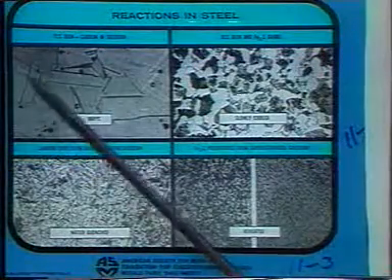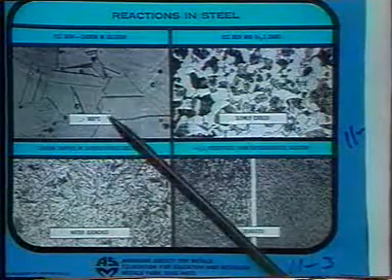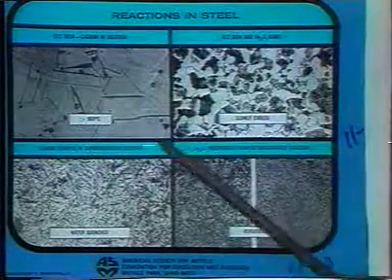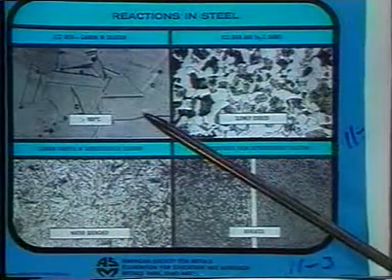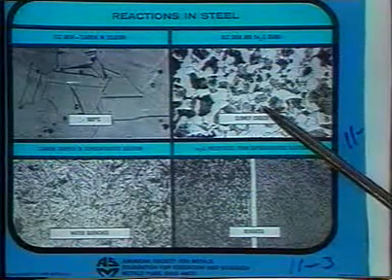Actually, these perfectly straight lines are also crystal boundaries, but they are special crystal boundaries called twins. But all of these things are crystal boundaries, and it's no identifiably different material. The little pockmarks you see in this particular case happen to be holes in the material, but it's not a solid state phase. If he would take that particular material and very, very slowly cool it, he would wind up with this as a microstructure.